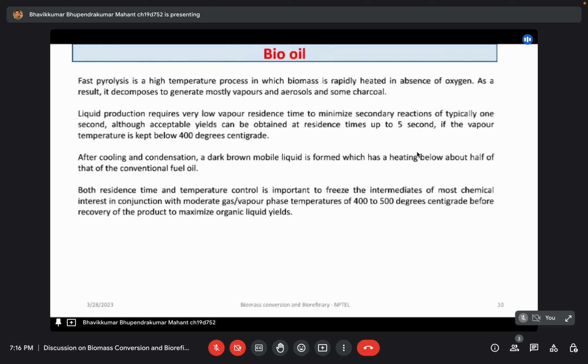Now we shift to bio-oil, because some questions are from the bio-oil section. As we discussed, if you want to produce bio-oil along with biochar, then you have to go for pyrolysis, that too fast pyrolysis. The residence time is up to 5 seconds, so your biomass is in the whole pyrolysis setup for very little time, and the temperature is kept below 400 degrees centigrade. Then you will get a dark brown liquid, which has a heating value about half that of conventional fuel oil. So you get the biofuel with half the heating value of conventional fuel oil, but you can use it in applications related to fuel oil. The important parameters here are the residence time and temperature control. If you want to maximize the organic liquid, you have to play with these two important factors.